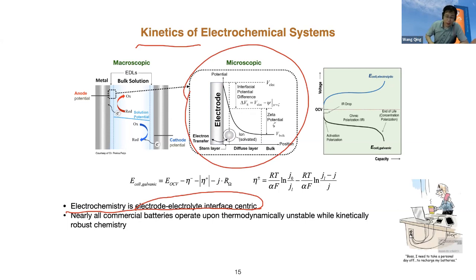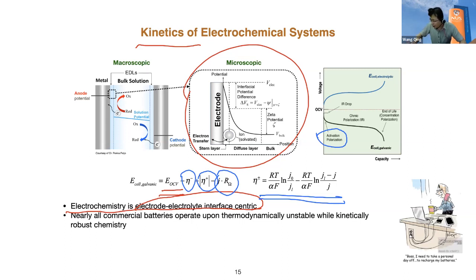And once you have current flowing through the system, your system will deviate from equilibrium, and then you have the overpotential. So the potential will be different from the one you measured at the open circuit state, that's equilibrium. You may have this overpotential for one electrode, for the other electrode, and also for the ohmic series resistance. A very important topic in electrochemistry is to study the dependence between the overpotential and the current, for the different kinetic processes. You may have activation polarization together with concentration polarization, so you may have the overpotential observed at the interface, and also ohmic polarization. Altogether, it will determine your voltage during the discharge process and during the charging process.